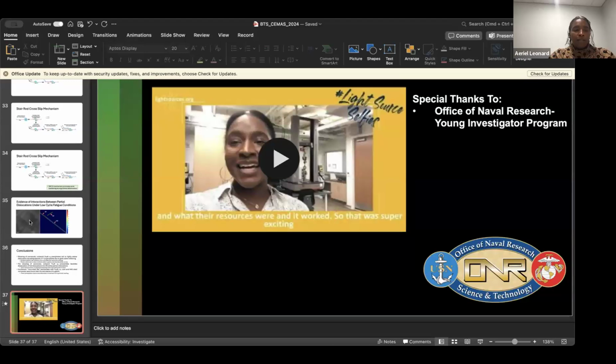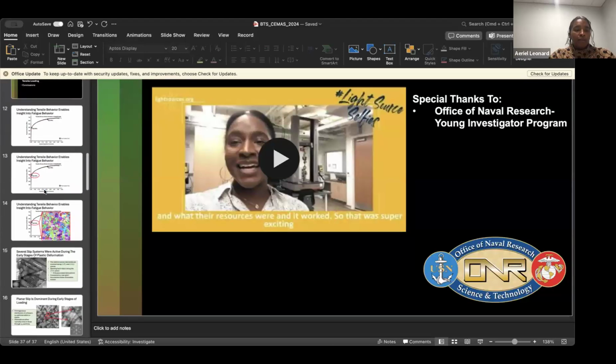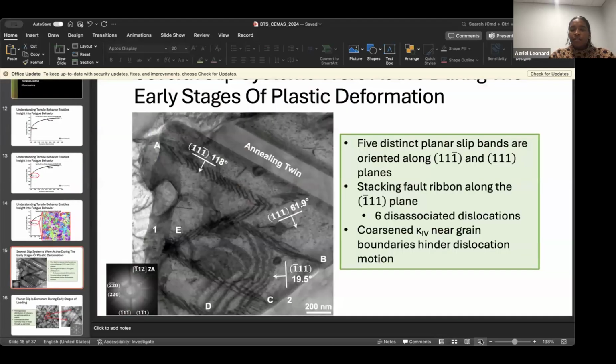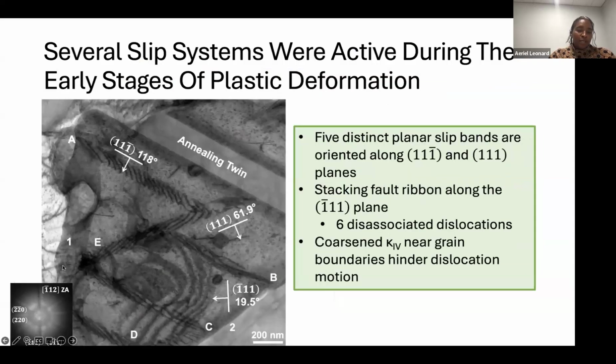If we go back to the original presentation, to when we were looking at the yield stage, this was basically what we were seeing. Here they are sitting near the boundary, and it was hard to tell if this was an initiation point, because of the curvature. There was definitely some relaxation, but either way, you could definitely tell that they were preventing dislocation motion. So yes.